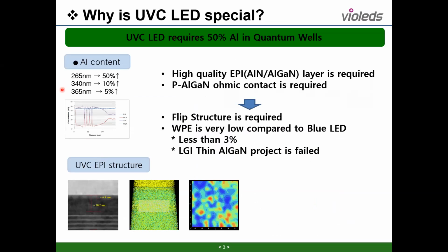So as I said, aluminum has a very important role in making the UV LED. In our current UVC 275, the aluminum content is more than 50%, and gallium is the other 50. Here you can see the SIMS data, and you can see the content of the aluminum and gallium composition. To make the LED quantum well, there is some ratio difference of the material, the well and then the barrier. For the 275, about 50% is aluminum, and then the other is gallium. UVC is almost 50%, and for the UVA 365, the aluminum content is less than 5%.